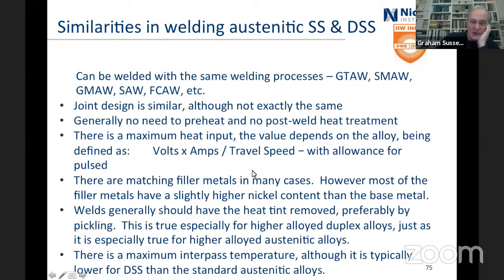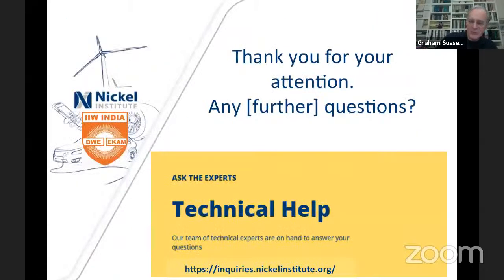And there are matching filler metals. All of those are going to have a bit more nickel content than the base metal, because otherwise you've got a bit of a problem. You really need to make your weld cathodic to the rest, so put a bit more nickel in. And you then take your heat tint off, preferably by pickling. And there's a maximum interpass temperature, although it's typically lower for the duplexes than for the austenitics. And that's it. Thank you.